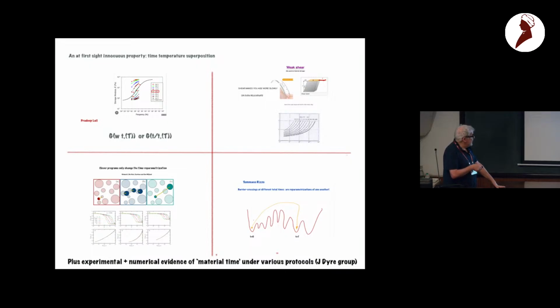And we checked. What we do is we plot a correlation against another one. So it's like comparing parts of a film: when you plot a correlation, a K mode against another K mode, time is gone. And we do it with the ordinary program and a variant of Ludovic's, which goes 100 times faster. It can go much faster, but we stayed at 100. And you see that the plots are straight, one on top of the other, which means that you are indeed watching the same film, only passed 100 times faster. This is quite counterintuitive.